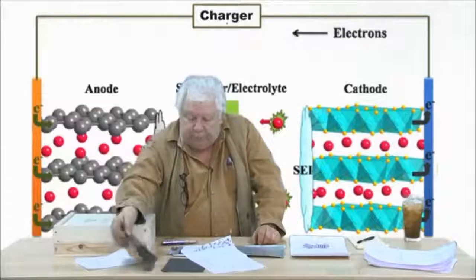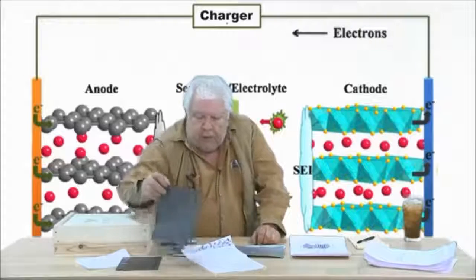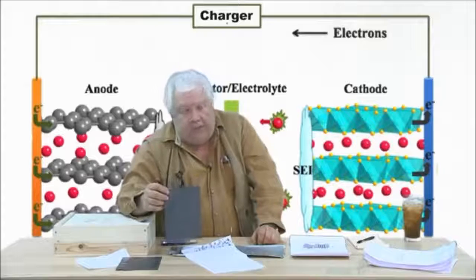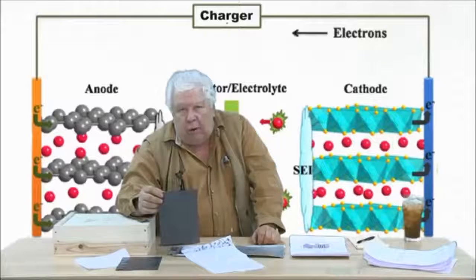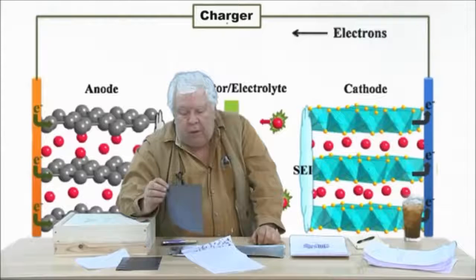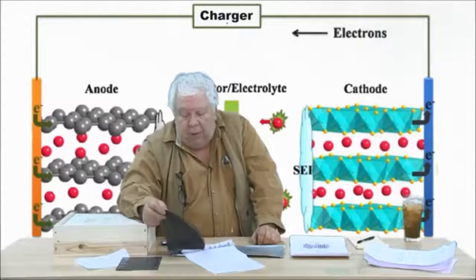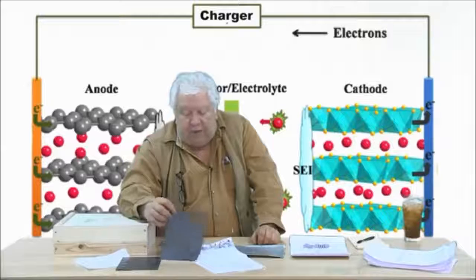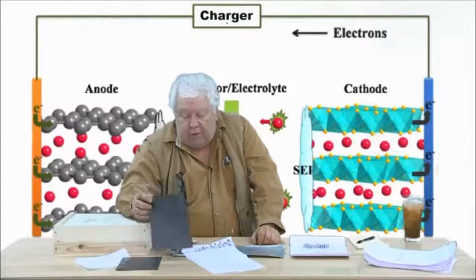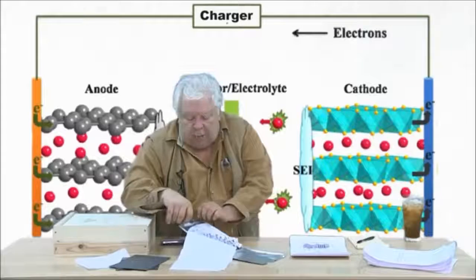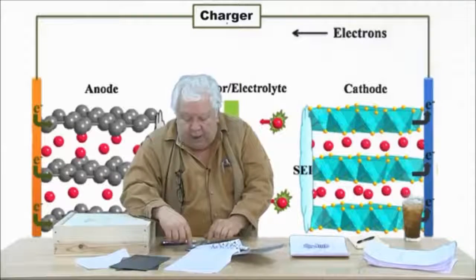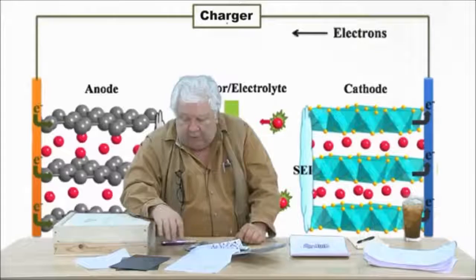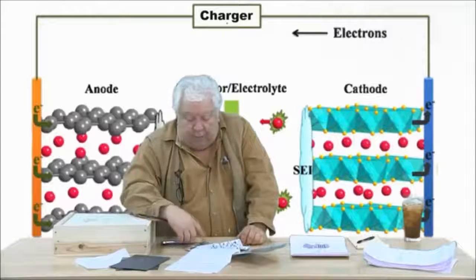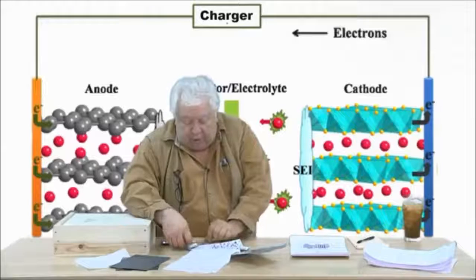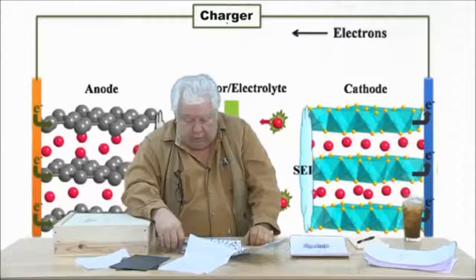we're at 0 volts. And then our anode is copper with graphite, graphene, carbon black, hard carbon, or some mixture of all that, again in a very fine powder that's mixed with the same polyvinylidene binder, and basically printed on each side of these very thin foils. Then the foils are gathered at the top and connected to these tabs. These I've torn off, but they alternate, so that all your copper ones are connected to your negative terminal, and all your aluminum are connected to the positive.